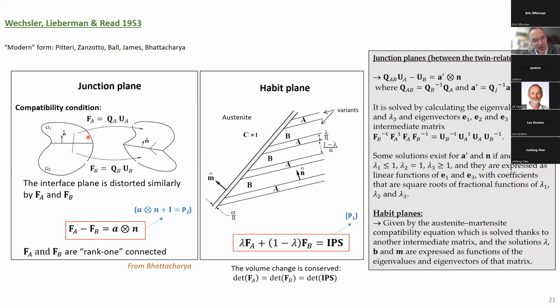We consider here austenite, okay? And here one part of austenite will become one variant of martensite, and another part of austenite will become another variant of martensite. And we want each of them to have their own transformation, which we can decompose by polar decomposition into a stretch matrix and a rotation matrix. But what is important is that at the interface, I should not create holes or overlap.